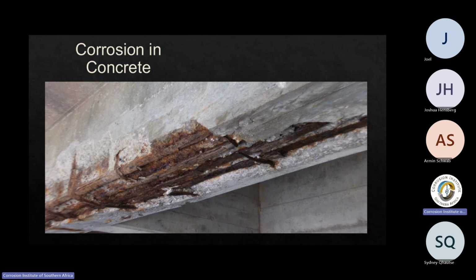Not just that, concrete is porous. So it's going to start attracting all the stuff from the outside as it goes through the hydration process of curing. And as it goes through that process, when it gets to the rebar that's inside, the concrete starts spoiling, and you can actually have degradation. I call it corrosion of concrete, but concrete doesn't actually corrode, it degrades. It breaks down because of the actual build-up of rust around your rebar inside. It starts putting pressure on it, and then you have this type of setup.